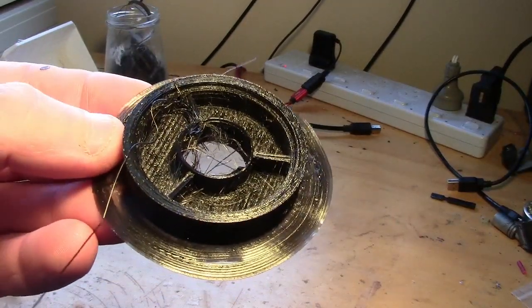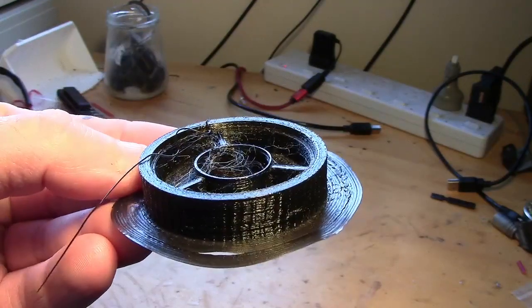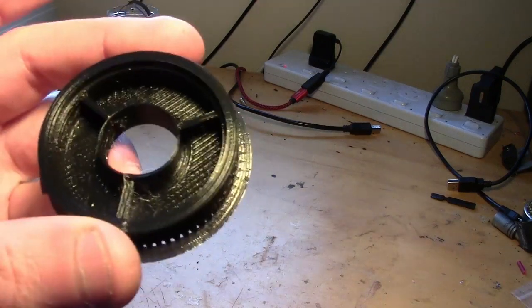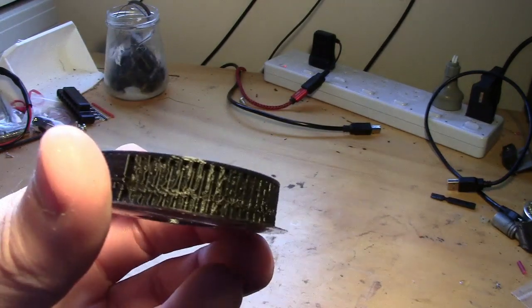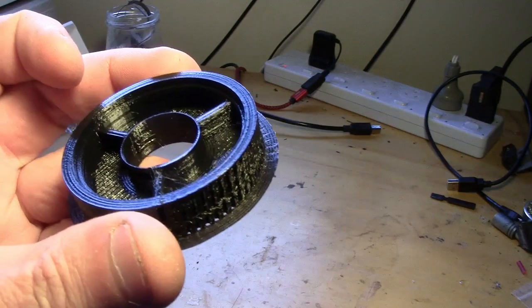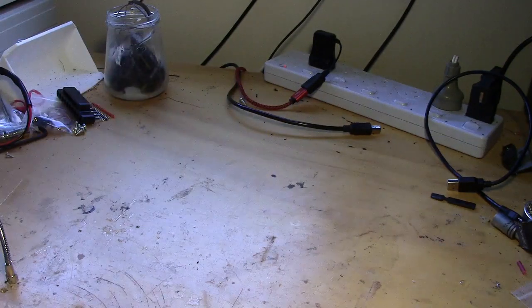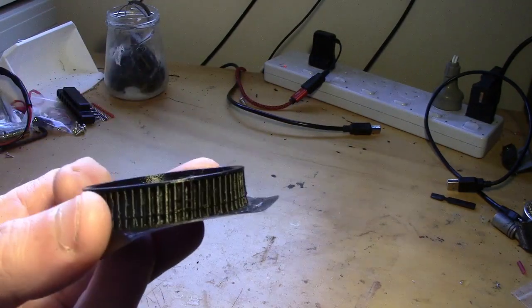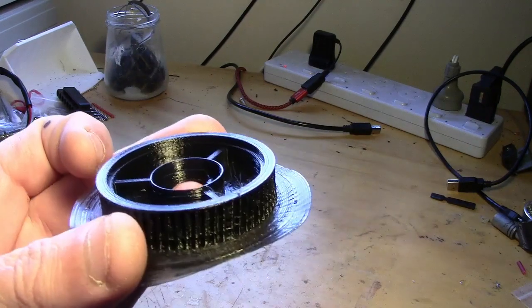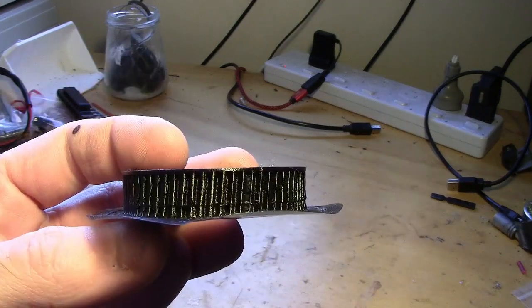help with this. The strings and poor finish of this gear are because of moisture in the filament, which is the biggest challenge of working with nylon. This print shows the same gear after I dried the filament, and it has a much nicer finish, although I trashed the gear teeth by using a default extrusion width that was too great. So I reduced that and made the final print shown here.